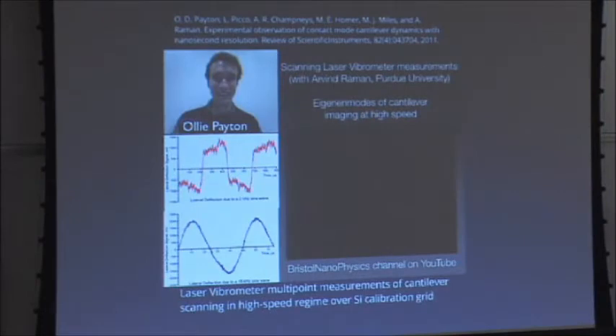So how does this work? Why aren't we destroying the sample? The clue came very early on. This was actually in Lawrence's thesis. We measured at low speeds the friction force, the lateral force. And then as we wound the speed up, there was a transition. It went from this kind of square wave to this sine wave. And it's a sine wave because we're moving the stage sinusoidally to avoid resonances at turnaround. So what you're seeing here is a force that depends on velocity.